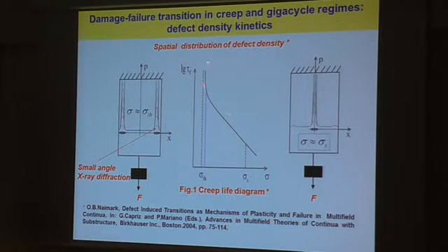This is a creep dependence: characteristic time of failure versus applied stress. It was found that the defect density distribution in this linear portion of the slope, a well-known case, corresponds to the nucleation of cracks in the near-surface area. But it was established also that when we approach some limit, and within some characteristic area, you can see a hot spot of damage localization in the bulk of the sample.